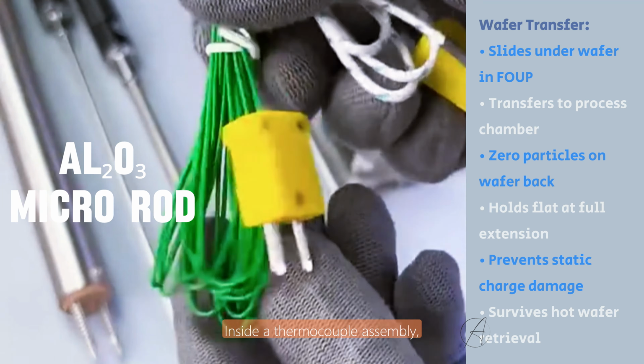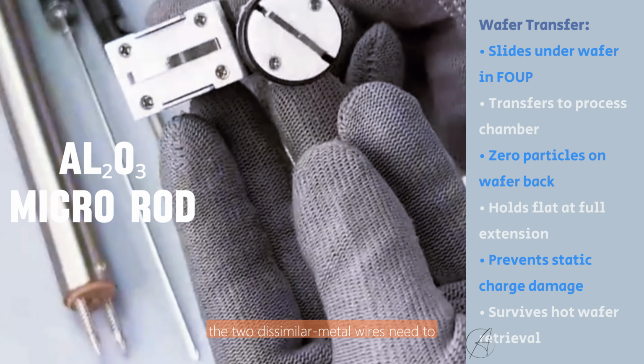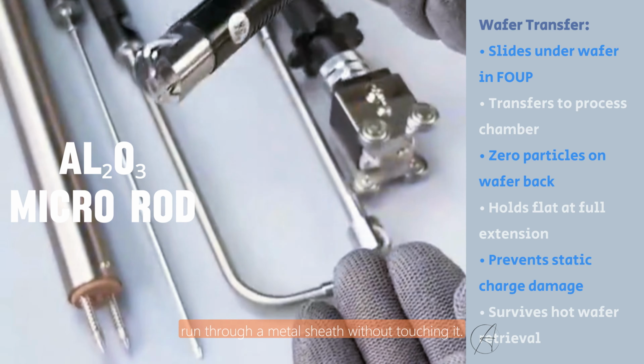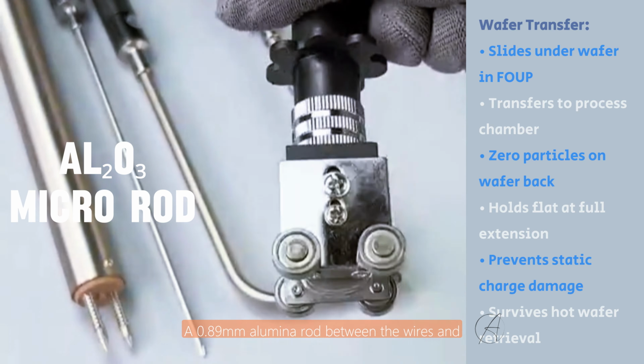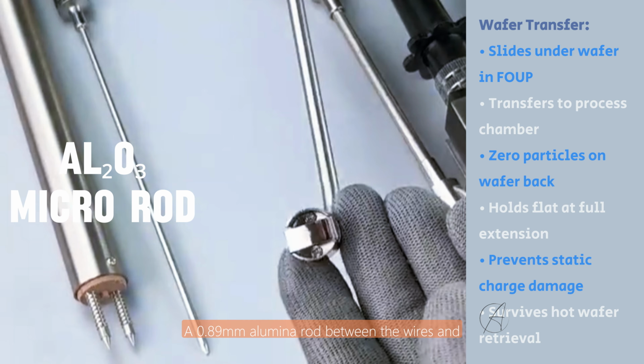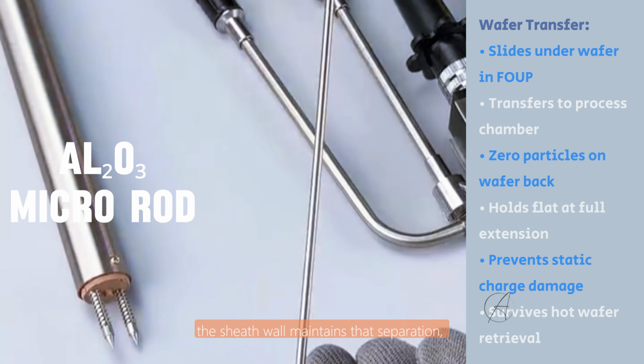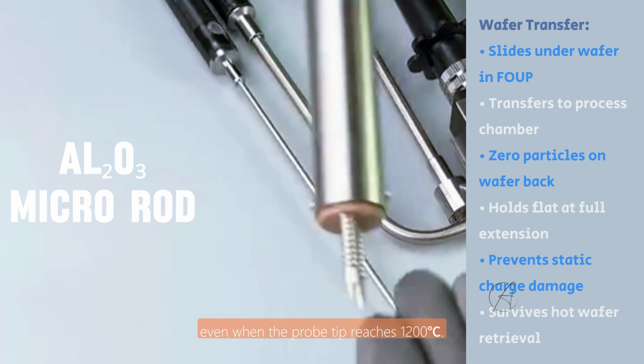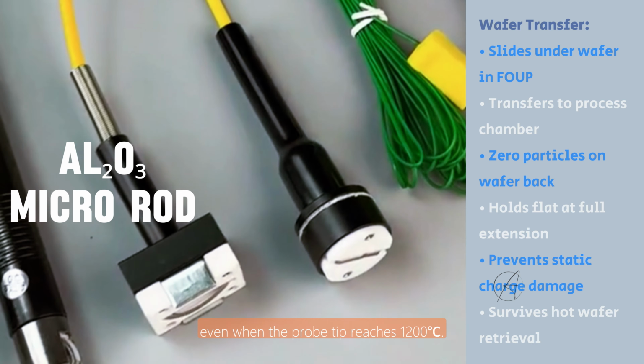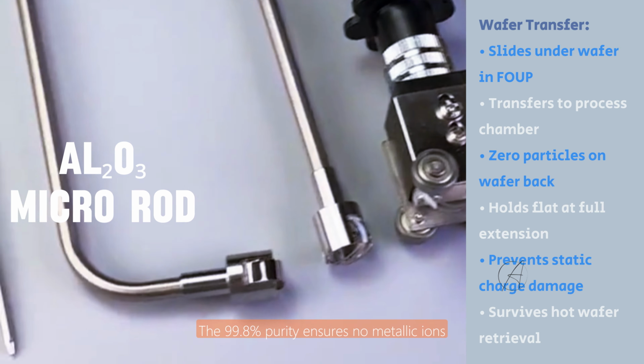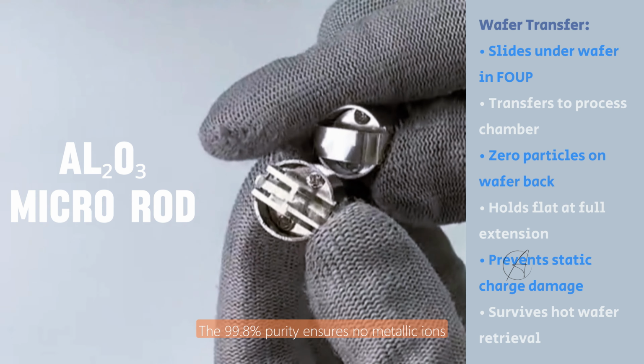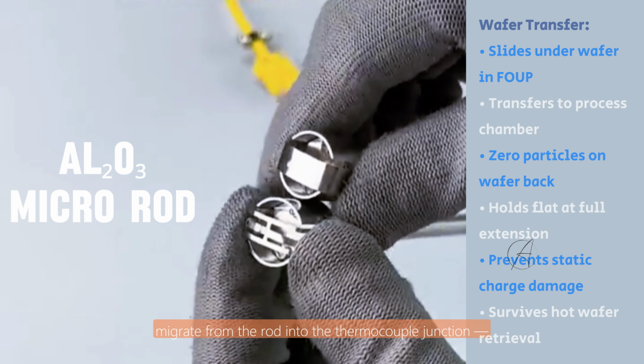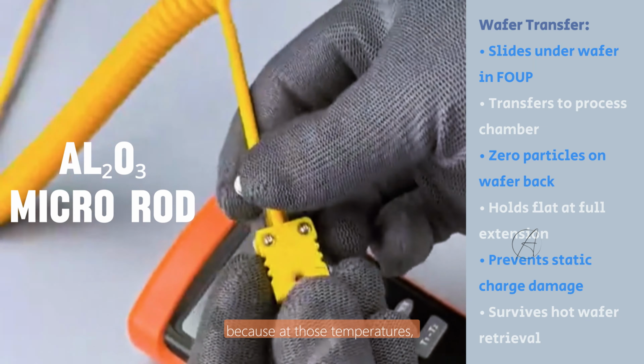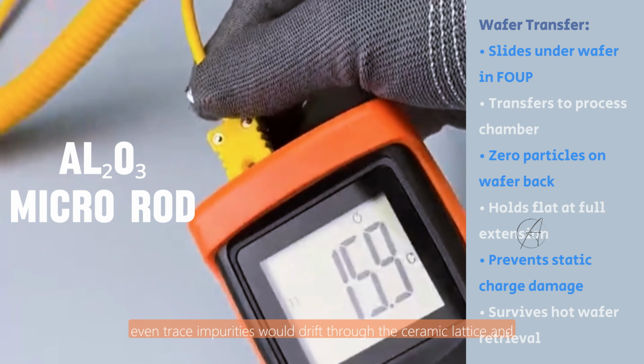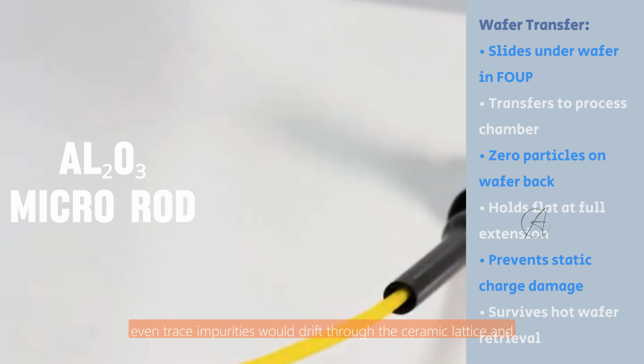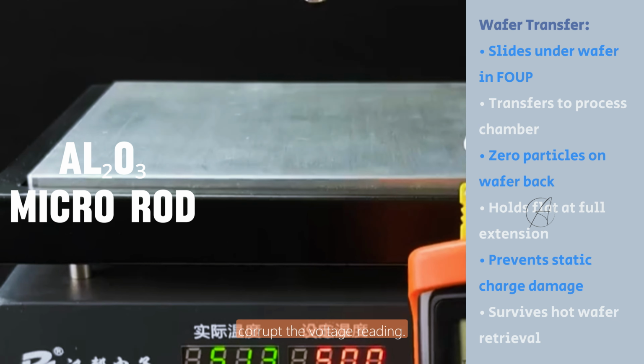Inside a thermocouple assembly, the two dissimilar metal wires need to run through a metal sheath without touching it. A 0.89 mm alumina rod between the wires and the sheath wall maintains that separation, even when the probe tip reaches 1200 degrees Celsius. The 99.8% purity ensures no metallic ions migrate from the rod into the thermocouple junction, because at those temperatures, even trace impurities would drift through the ceramic lattice and corrupt the voltage reading.